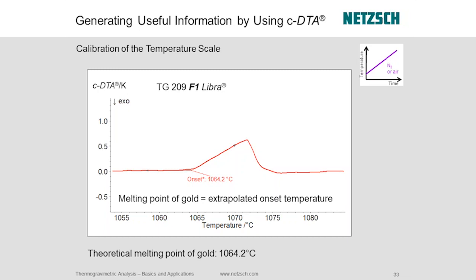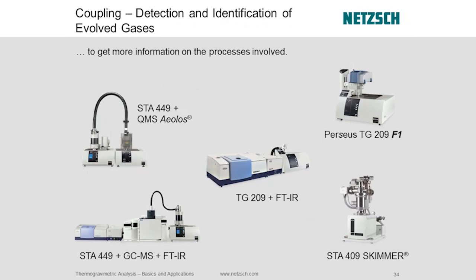But now, using this CDTA, calculated DTA technique, we can very accurately use metal melting points to calibrate the furnace temperature. So that's another good reason for the CDTA. We can use these standards to get within a tenth of a degree or so inside the furnace, compared to, I don't know, 10 or 20 degrees in your old style TGA. Okay, so accurate calibration and also identification of things like melting points or other transitions. Okay, that's CDTA. We'll talk for about 5 minutes now about coupling.